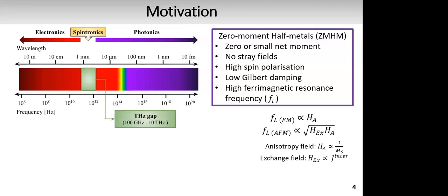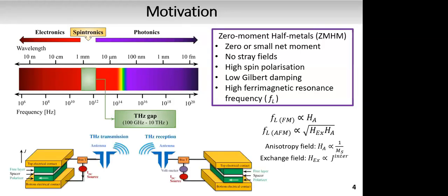So as I mentioned, the first member of the zero-moment half-metals was manganese 2 ruthenium gallium. And here I am showing an illustration of a chip-based heterodyne terahertz transceiver based on a zero-moment half-metal material in a spin-torque oscillator. In such devices, the stray field would be negligible, hence crosstalk between magnetic elements is minimized. The high ferromagnetic resonance frequency means the device can operate in the terahertz frequency range, and high spin polarization ensures a high TMR ratio.